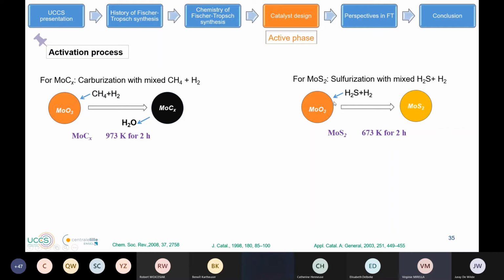So first of all, I would like to talk to you about the activation process of the catalyst. This is really important, the activation process. When we have the oxide, it is not the active phase. So from the oxide, we need to form the active phase that will convert our syngas, hydrogen and CO, to our olefin. So to have molybdenum in a carbide phase, we activate under a flow of methane and hydrogen at high temperature for 2 hours to have our molybdenum carbide. For our sulfur catalyst, we use the oxide molybdenum catalyst, and we treat it under a flow of hydrogen and H2S to have our molybdenum sulfide at 673 Kelvin for 2 hours.